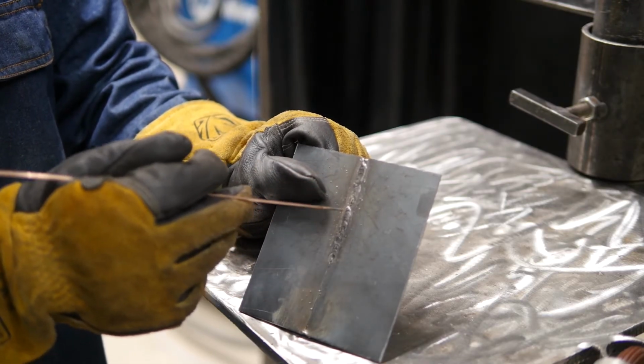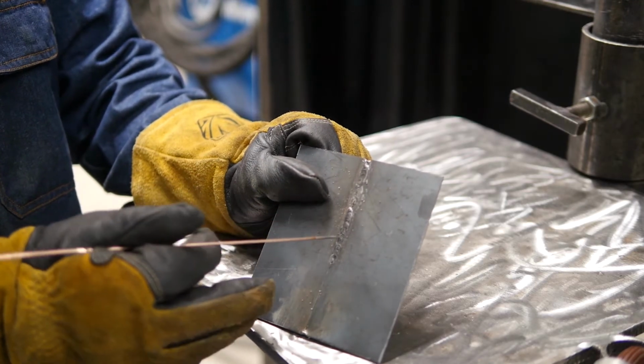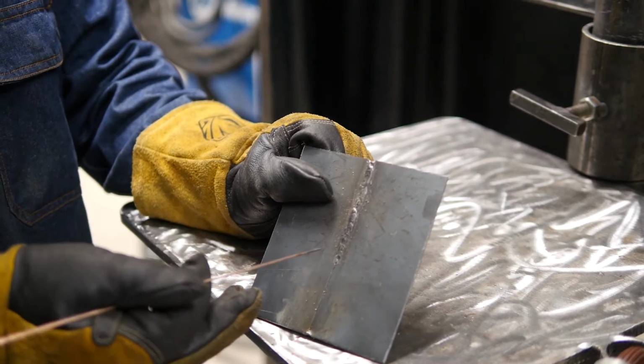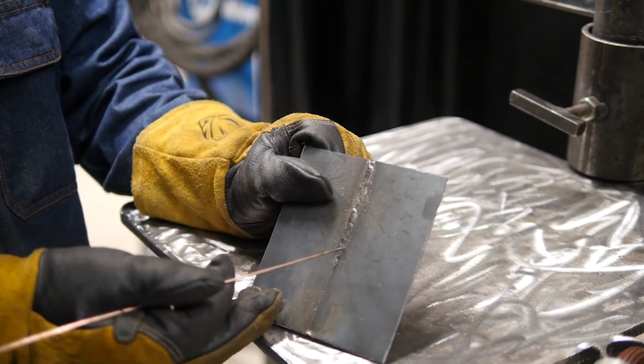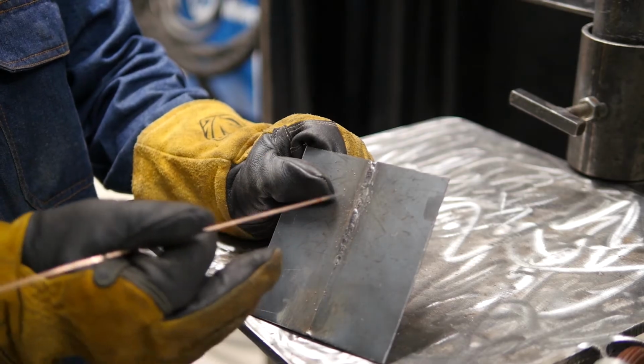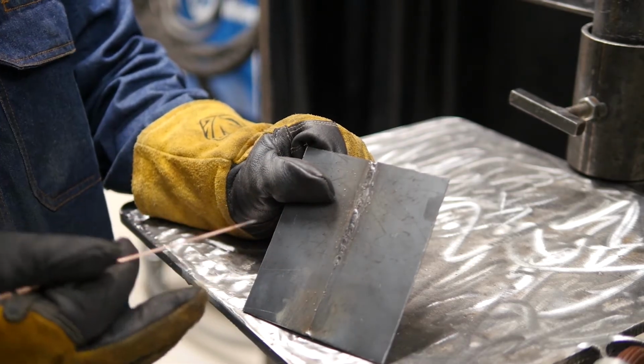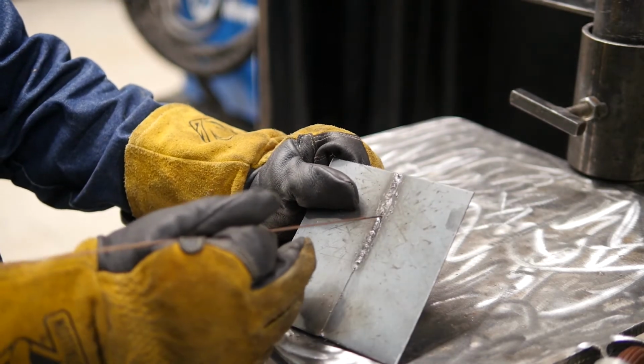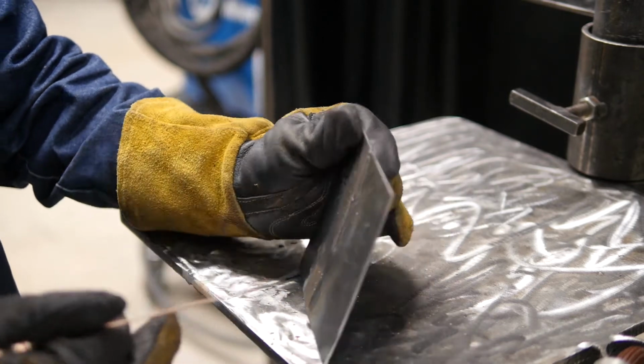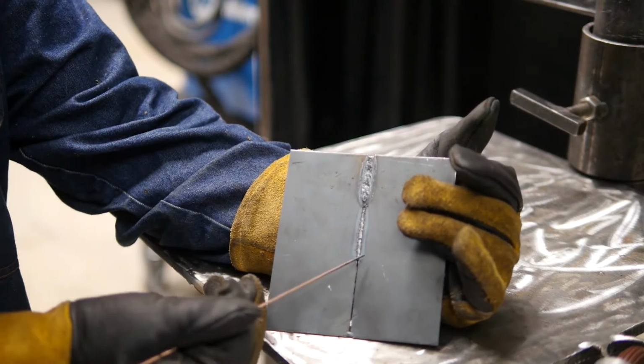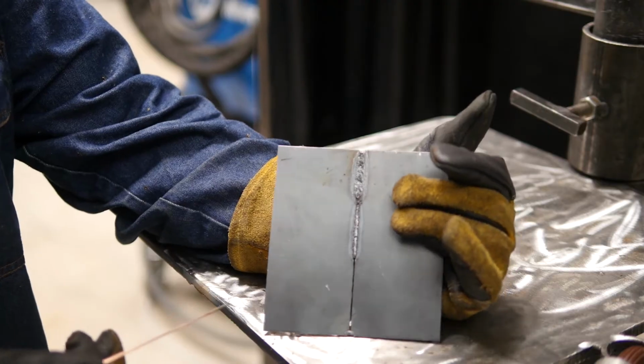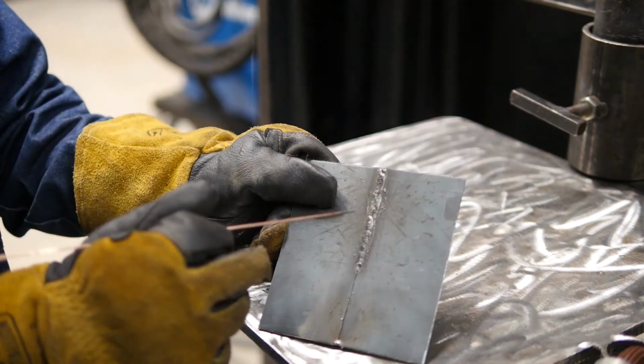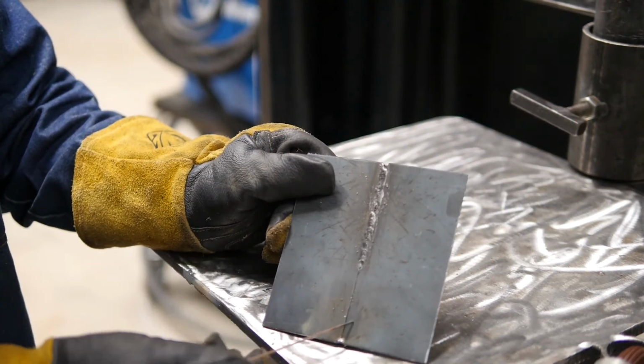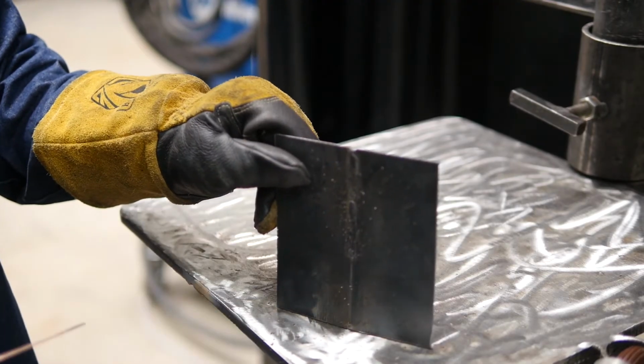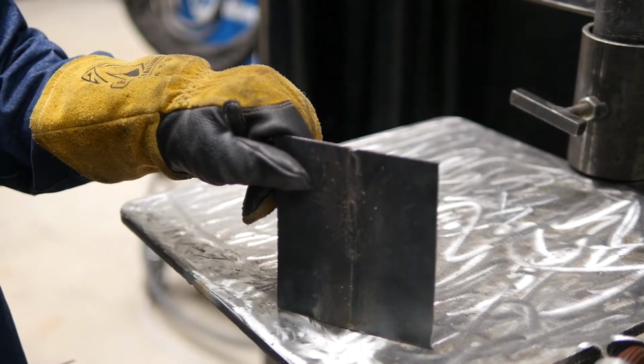But when I switched to my flat weld, I turned my procedures down. I turned the wire feed speed down to 50 and my voltage down to 14. That's as low as the book recommends you run this wire. And I got a much better result on this side. Back side of the weld also looks quite a lot better. So let's try those same procedures here, only here, but we'll put it back in our vertical position and see if we can get a nice looking weld.